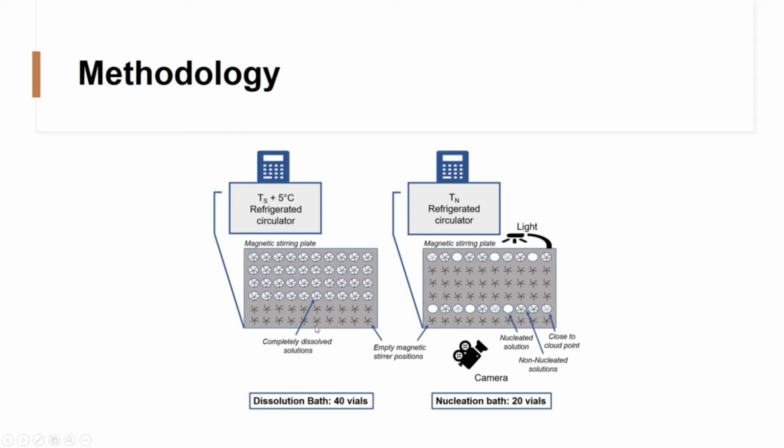So what Shibangi did is she did this type of experiment. She started with 40 vials in the first water bath, and then after 1 hour she moved to the second water bath, and then she monitored the time at which each vial got nucleated until she observed nucleation in the 40th vial. So that's the experiment. And then she did this experiment for 5 different supersaturations. So I think it's 1.3, 1.5, supersaturation of 1.76, 2, 2.26, and 2.57.